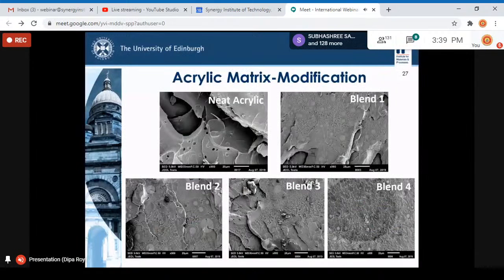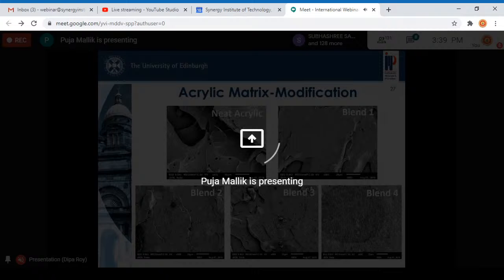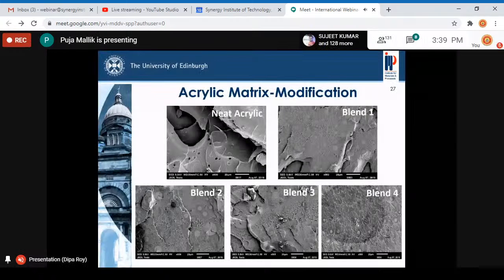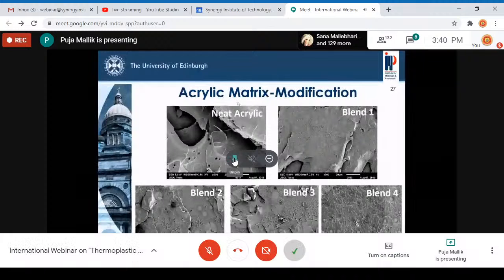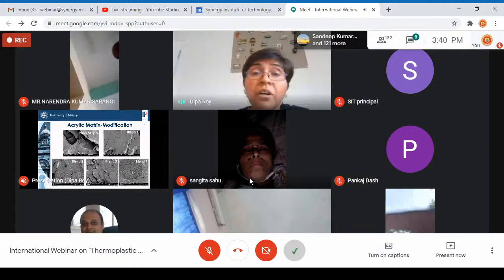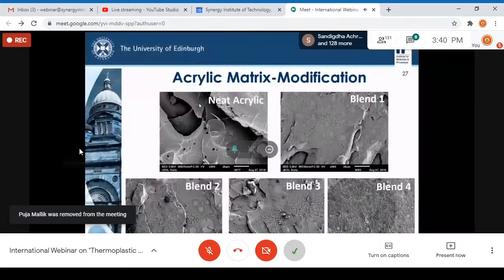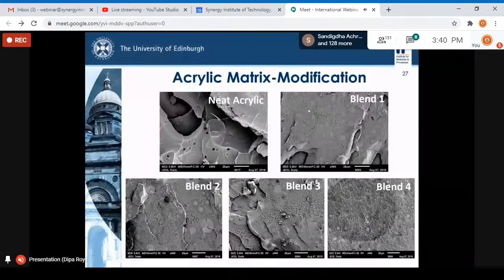Now, we prepared 4 blends, varying the ratio of this polyphenylene ether between 3 to 15 wt%. And you can see here some scanning electron micrographs of the blends. The first one is the neat acrylic. This is the pure acrylic resin. These are some of the voids. This resin is very prone to foaming when we want to cast at room temperature, so it's very hard to prepare pure acrylic samples. Now, when we have the blends, the foaming tendency is reduced significantly. So we don't see any voids in the blends, but we can see these zones.